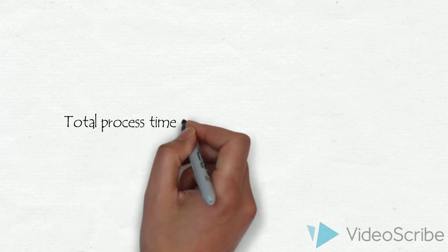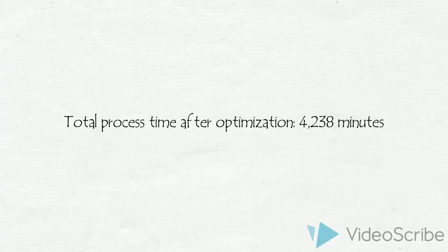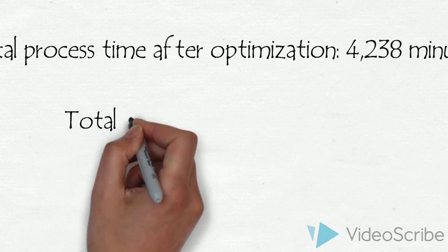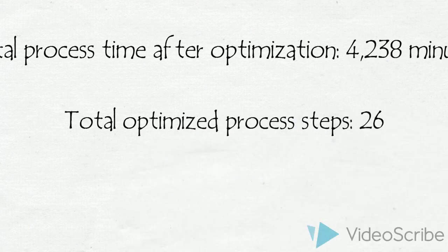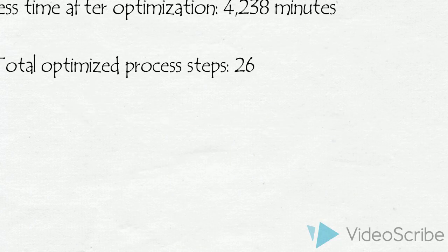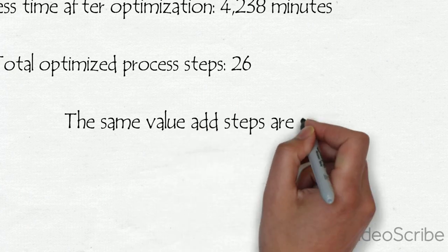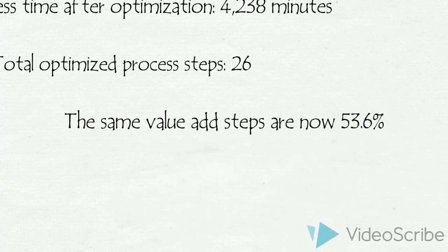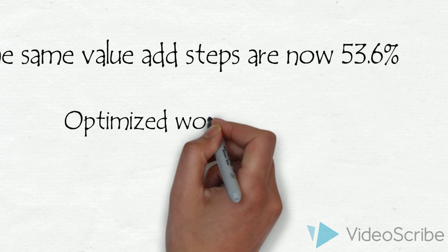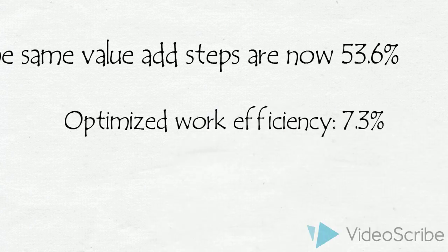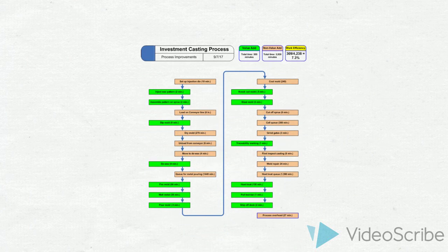This saw the total process time drop to 4,238 minutes, total steps dropped to 26. This in turn raised the percent of value-add steps up to 53.6%, and optimized work efficiency increased to 7.3%. Then I generated a third and final flowchart detailing the optimized process.